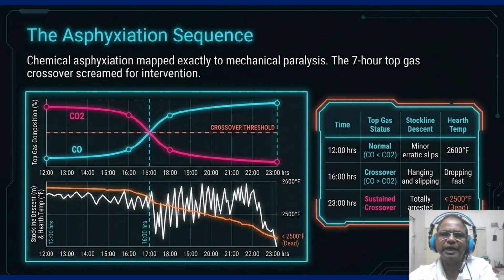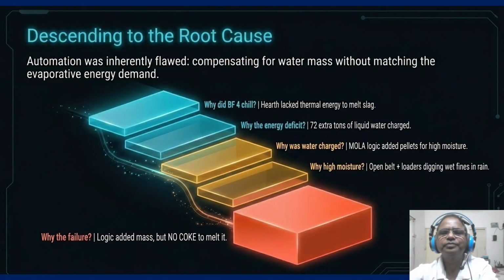You must monitor gas ratios as if they are the furnace's pulses. To prevent this from ever happening again, we have to peel back the layers and descend to the absolute root cause. So, descending to the root cause. Look at this 5-why staircase as it is shown, the descending blue and the orange. So why did this hearth freeze or get cold? It lacked the thermal energy to melt slag. Why the energy deficit? Because 72 extra tons of liquid water were charged.